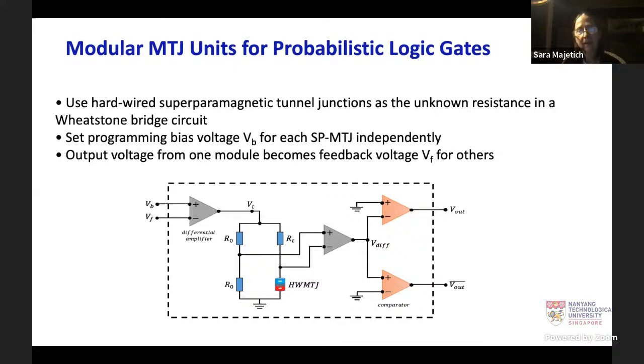So you need the time average. So we don't have coherence, we have the stochastic process. But if the stochastic process is happening fast enough and you average over a time window so that you get a reliable average that's not changing as you increase your window, then you get the statistical average. So it's a different approach, but you don't have to deal with the coherence problem. Thank you.